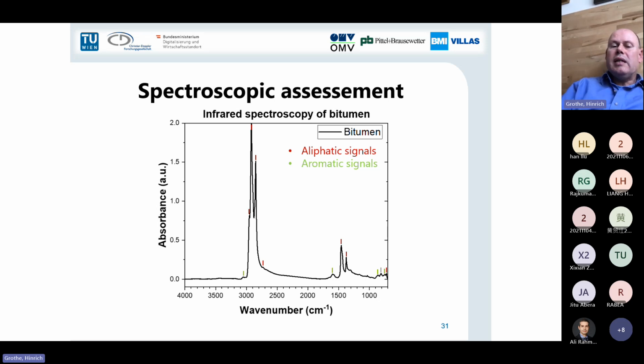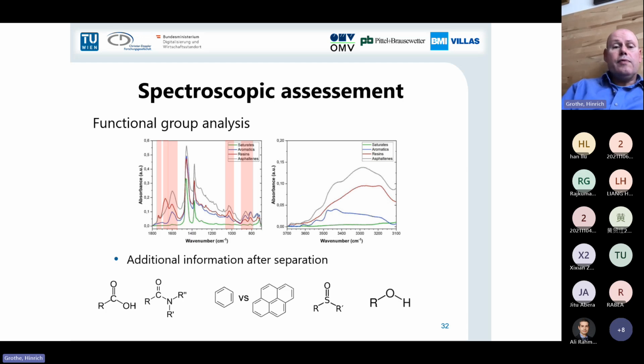But in general, the infrared spectrum of the whole bitumen gives not really a lot of information. But if you apply SARA fractionation, that means if you apply this polarity chromatography, which I was speaking about before, you see the different fractions: the saturates, the aromatics, the resins, and the asphaltenes, and they give different infrared spectra. So now the situation becomes much more clear, and you get much better spectra and much more chemical information after the separation into these four fractions.